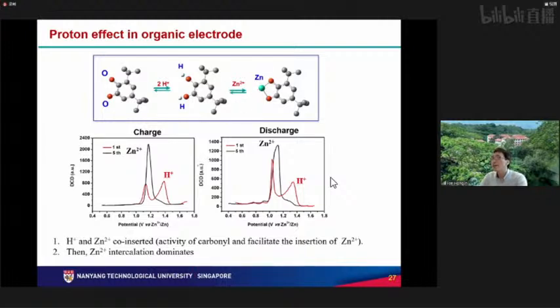Okay, this can be confirmed indirectly from the differential charge and discharge curve. In the first cycle we have zinc, and also proton. In the fifth cycle of charge, the redox peak corresponding to proton is much reduced, so the peak corresponding to zinc uptake is more dominating. That means maybe the proton comes in only in the first few cycles. It will not be dominating in subsequent cycles. The same case holds for discharge. So this proton may cause some interaction at first, but zinc will dominate in the future. Of course, this is preliminary data.